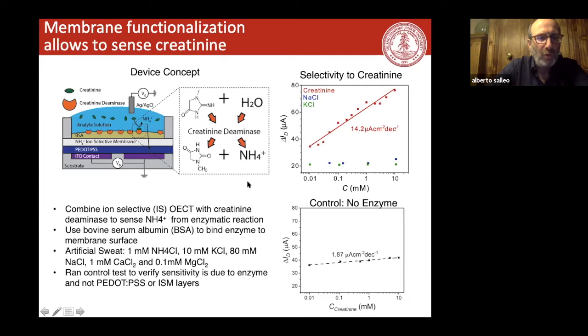So what we needed to do was immobilize the creatinine deaminase near the ion selective membrane. And it turns out the easier way to do this was with BSA, and then the creatinine deaminase was deposited on it. And this immobilized it for a while. And again, this is not really the best way to do it. We just wanted to demonstrate the concept that if you have an enzyme that degrades the desired molecule into an ion that you can sense, sort of expanding a little bit this ionic sensing, you can sense that molecule.